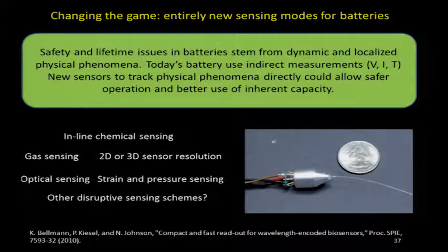But the materials aren't the only thing. It turns out the materials are better than the batteries, because you back way off from the ability of the materials to perform because of safety issues, longevity issues. For example, in our current batteries that are being sold commercially, we measure the voltage, the current, and the temperature, but it's the outside temperature. If you begin to measure the inside parameters, you can charge much more quickly. You can use, instead of half the battery, which is the level being used in a Chevy Volt or Nissan Leaf type car, maybe two-thirds and still have the same lifetime.